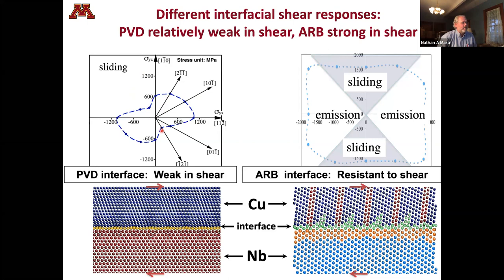If you compare this with what you calculate for the ARB interface, you'll find that that same yield surface gives us stresses that are always in excess of 1.5 GPa. So it's much, much stronger in shear. What does that mean? It means all those sliding mechanisms that we had in the PVD interface are not available in this case. They're turned off. So you get this very different kind of behavior.